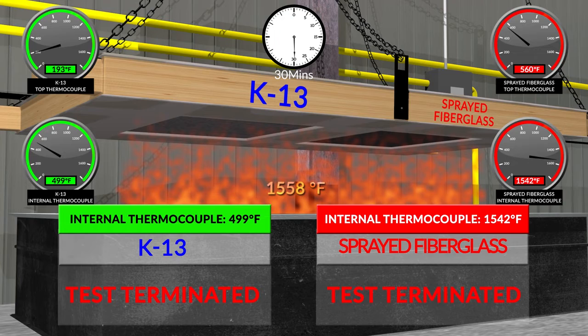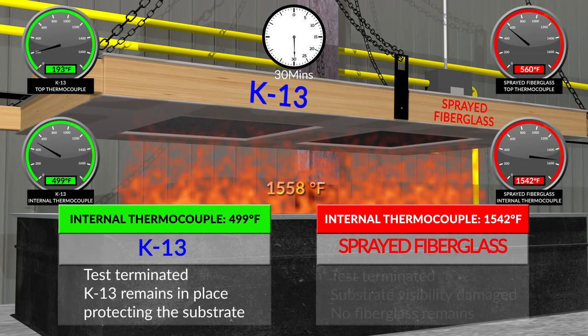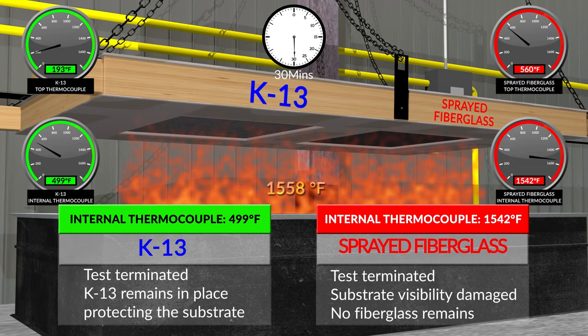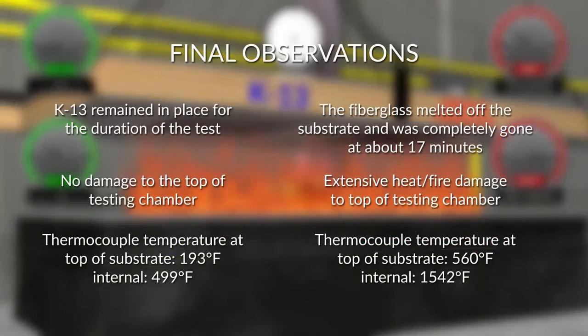K-13 test terminated. Sprayed fiberglass test terminated. K-13 test terminated. K-13 remains in place, protecting the substrate. Sprayed fiberglass test terminated. Substrate visibly damaged. No fiberglass remains. Final observation.